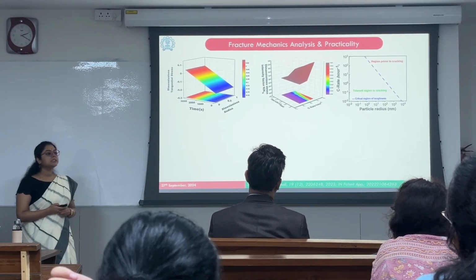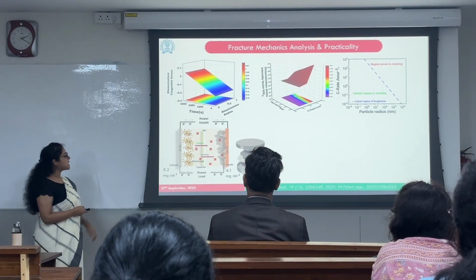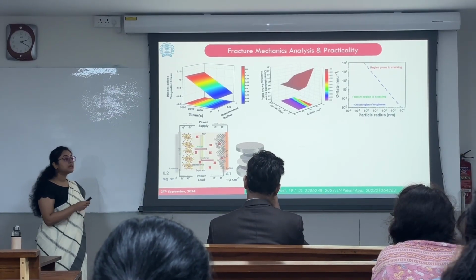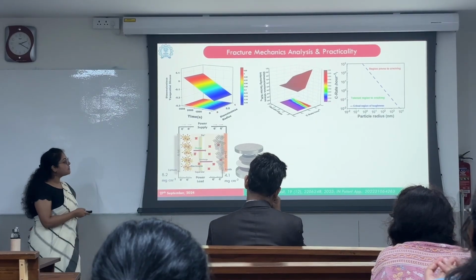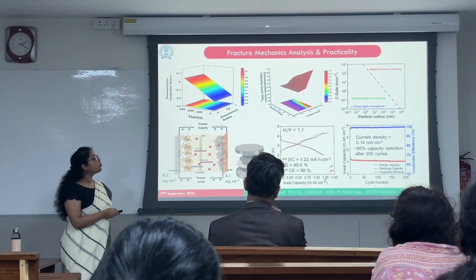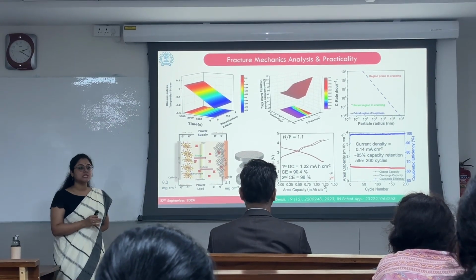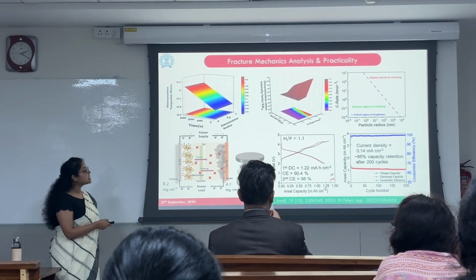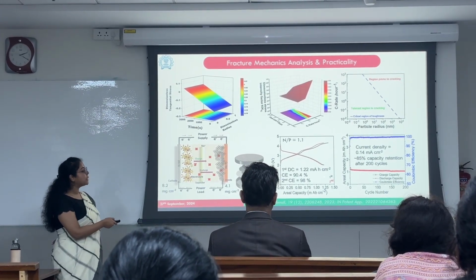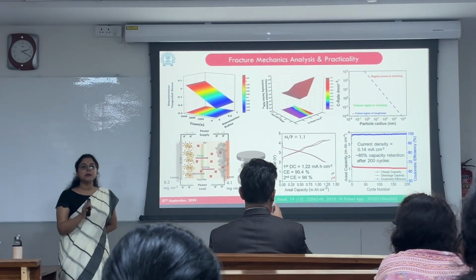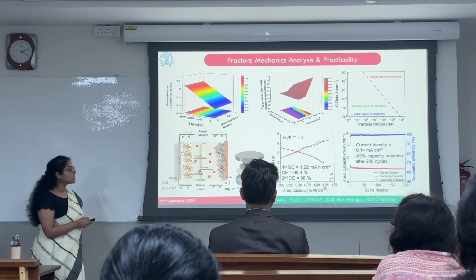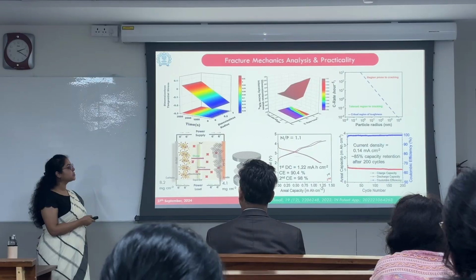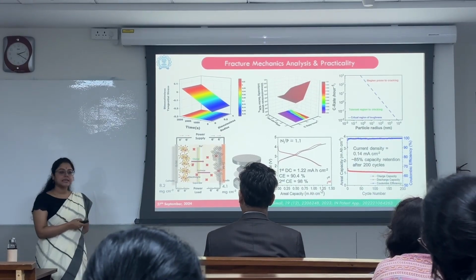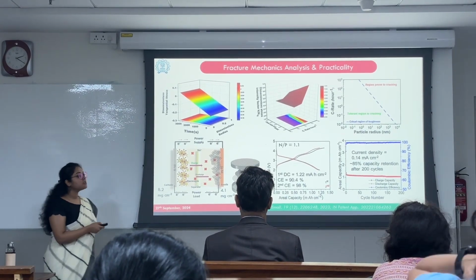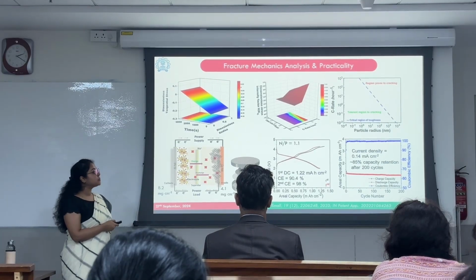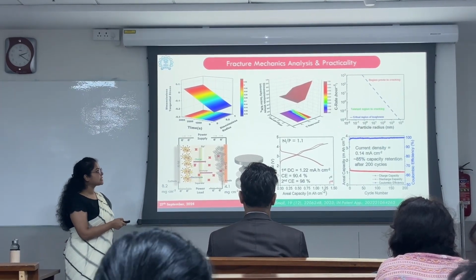To further validate the practicality, we fabricated a full cell against the biomass-derived pre-sodiated hard carbon anode, and we cycled it at a current density of 0.14 milliamp per centimeter square, which gives us a first cycle discharge capacity of 1.22 milliamp hour per centimeter square. However, the Coulombic efficiency was only 90.4%, which further increased to 98% from the second cycle onwards. And the capacity retention delivered was around 85% after 200 cycles.